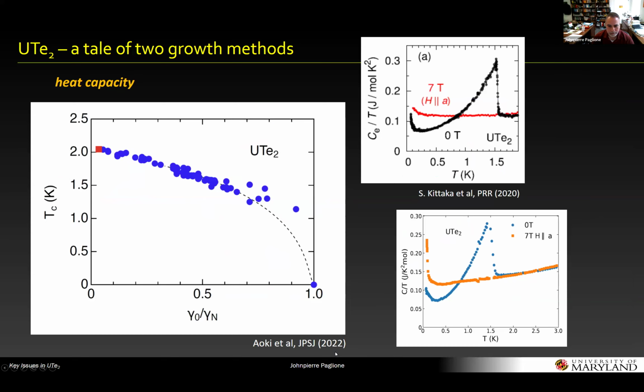Here's a plot that was published a couple of years ago by Aoki, and it's probably been updated since, but this is the best I could find with the most up-to-date data, including the highest TC samples and the lowest residual heat capacity. I don't want to call it gamma because I don't think it's an electronic heat capacity. It definitely doesn't show itinerant conduction, but it's a residual heat capacity nonetheless, and it seems to scale with TC. Okay, why? I don't know.